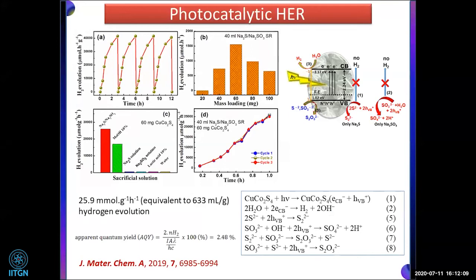Basically we know that the photocatalytic reaction is similar everywhere; you know already what is happening. We already discussed that on photoexcitation there will be exciton generation, the hole will be at the VB and the electron will be in the conduction band. And one more thing: if we do not add any sacrificial agent in this reaction, we do not get much hydrogen, because the holes will again recombine with the electrons, and we will get only thermal emission. So to stop that, we need the sacrificial agent, and we did the mechanism study.